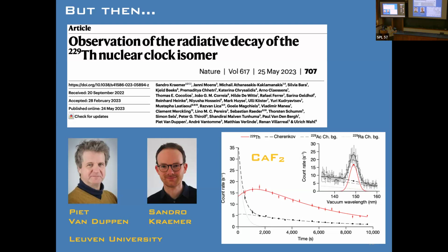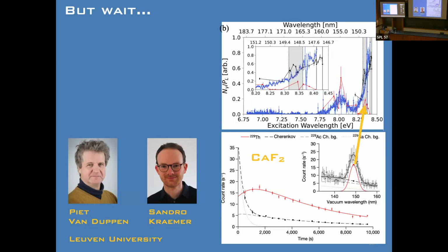Actinium-229 beta decays into thorium-229. And when it does, with a sizable fraction, it should feed into this nuclear excited state. And so he then took the crystal, put it in front of a spectrometer just to see if it was glowing, and if so, at what wavelength. And what he saw was a few nanometer wide feature around 150 nanometers. This was exciting for us because this was exactly where we had seen our quench signal. But it was also a little bittersweet because Pete saw a very long lifetime decay, whereas we had only seen this quenching decay. So we thought, okay, this probably really is the transition, but in our crystals, it's quenched.